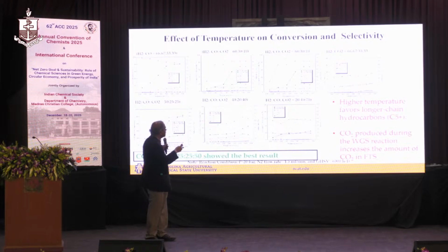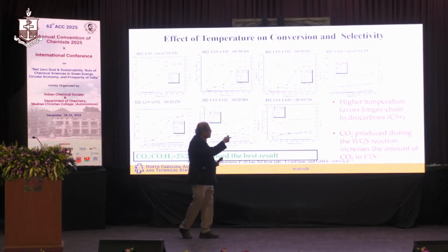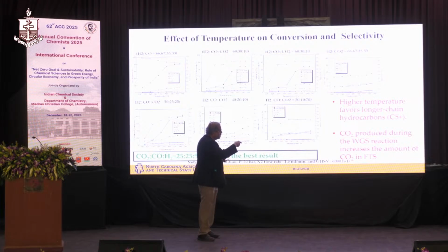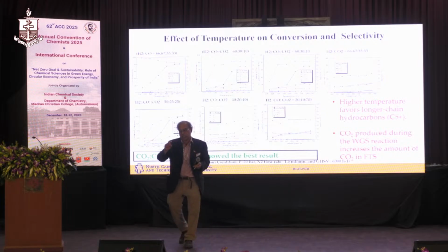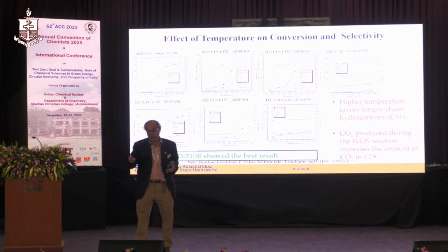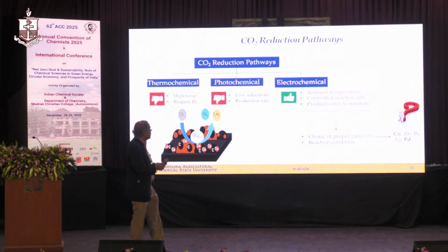All right? So now, I'm not going to go through all these details. What we found is that if you use 1 to 1 to 2, this ratio, that is the best result. And as you increase the temperature, you get these longer chain hydrocarbons, and then the water-gas shift reaction increases the amount of CO2. So it's a competing reaction. We are also producing some CO2. So this is what this is.